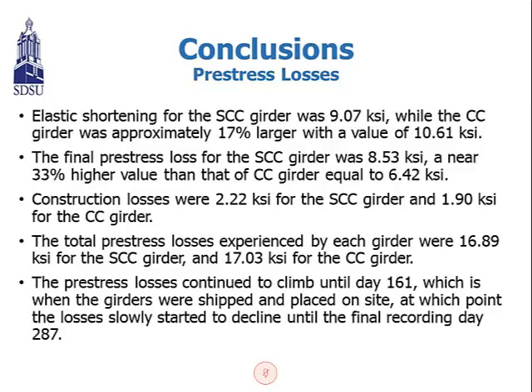And one interesting finding is from the prestress loss measurement. The prestress losses continued to climb until day 161, which is when the girder was shipped and placed on site. And then the losses slowly started to decline until the final recording day, 287.